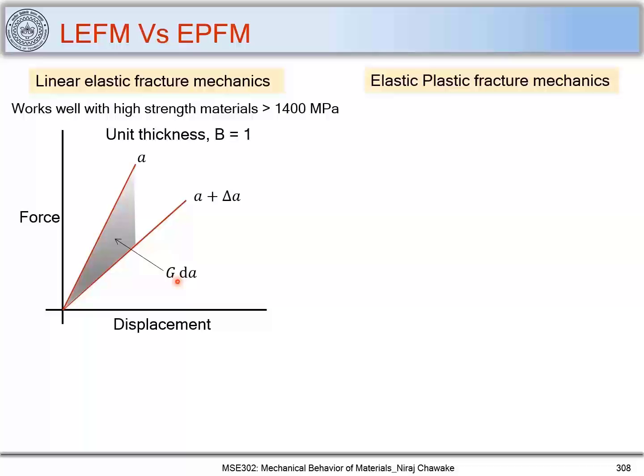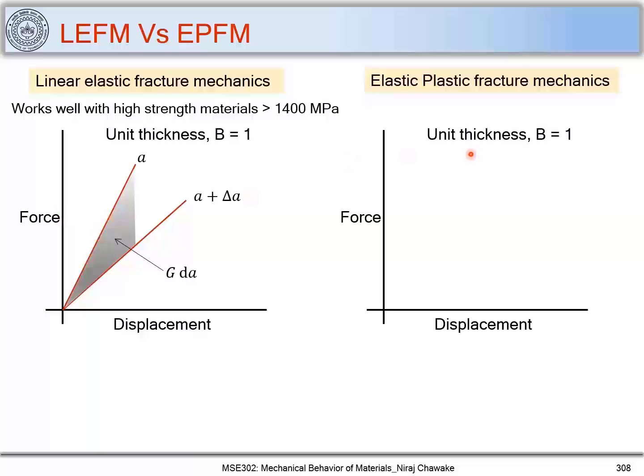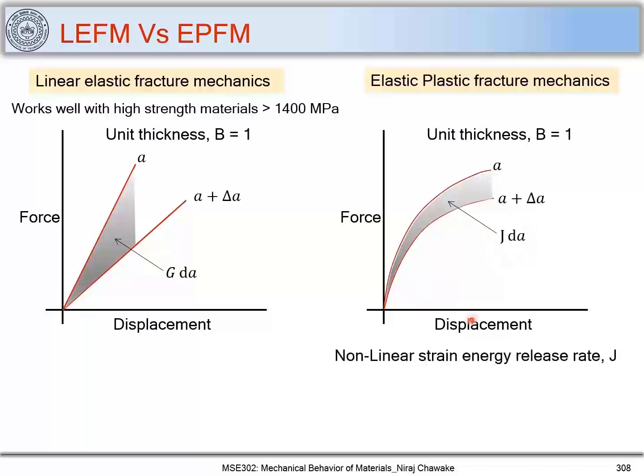Now when we look at elastic plastic fracture mechanics, we also plot force versus displacement. However, in this case, the variation of force with displacement is not linear. Let's consider the unit thickness of the sample to be 1, and you can see that for a crack length A, the force displacement relation is not linear. Now let's consider a crack length of A plus delta A. Here also the force displacement relation is not linear, and the energy release, which can be given as the area between these two curves, is called J dA. Here J is nothing but the non-linear strain energy release rate.